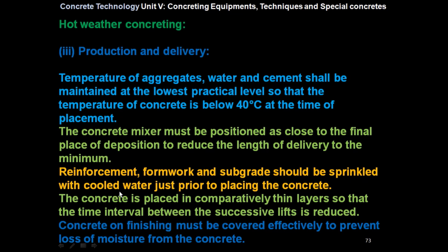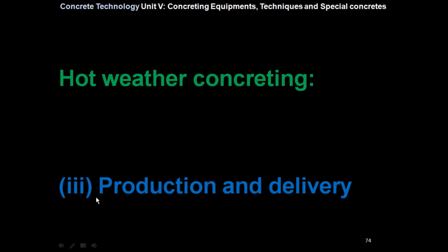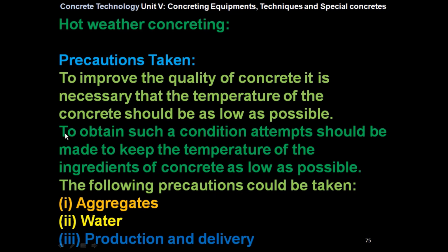Reinforcement, formwork and subgrade should be sprinkled with cooled water just prior to placing the concrete. The concrete is placed in comparatively thin layers so that the time interval between the successive lifts is reduced. Concrete on finishing must be covered effectively to prevent loss of moisture from the concrete. So we have seen the third, production and delivery, and the precautions to be taken in hot weather concreting.